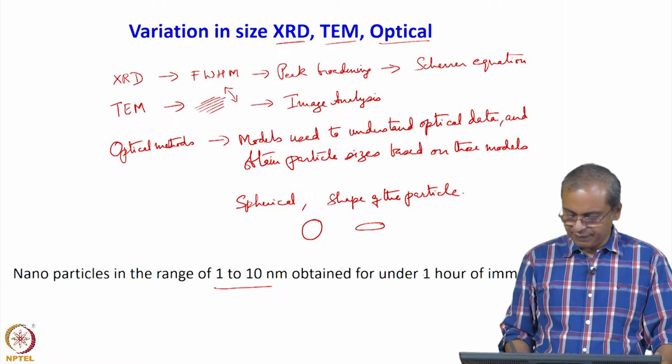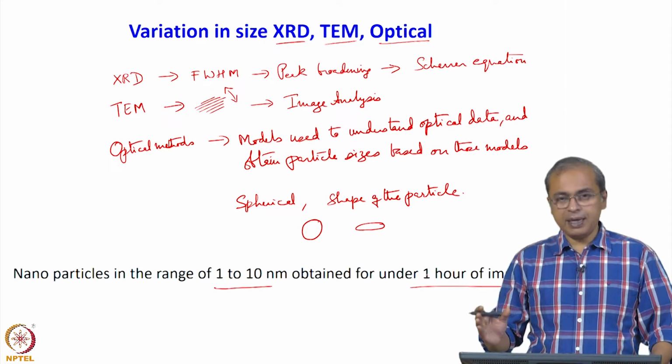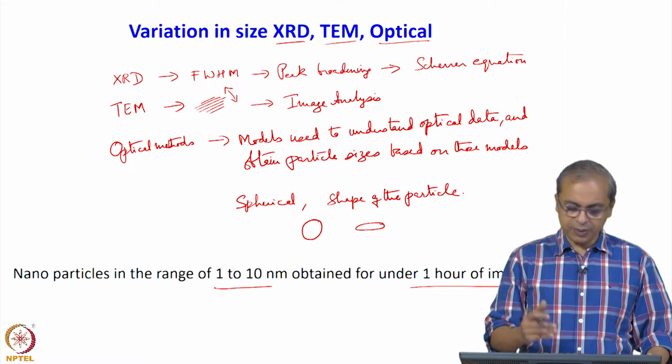Okay. So, let us say this is some kind of template assisted synthesis where you are immersing the matrix, the polymer, into the solution that has the salt for varying durations of time. You could have from several minutes to 1 hour of immersion, and then correspondingly a different amount of salt enters the system, and corresponding to that the crystal that grows when you expose it to H2S is of different sizes.